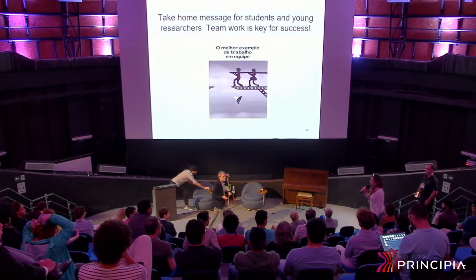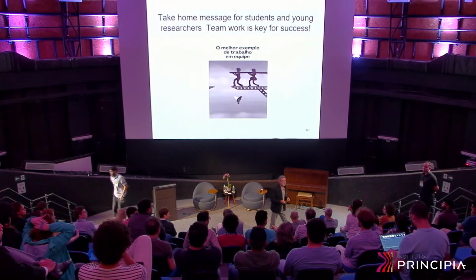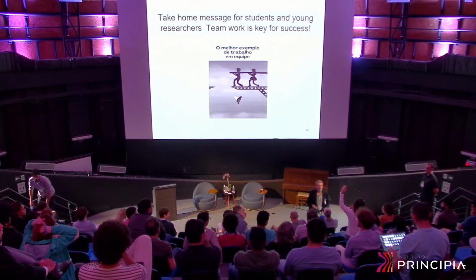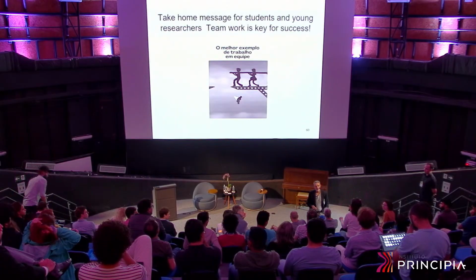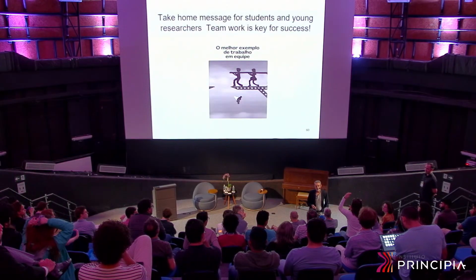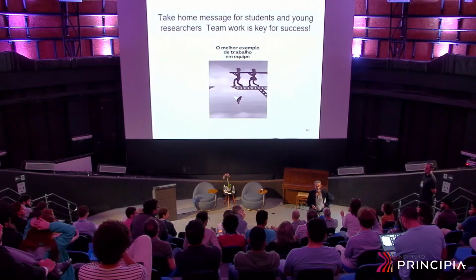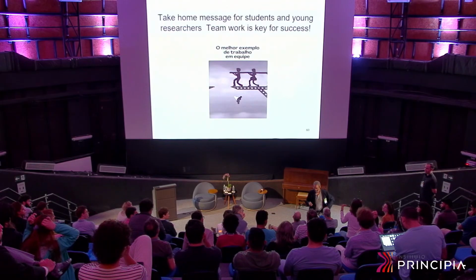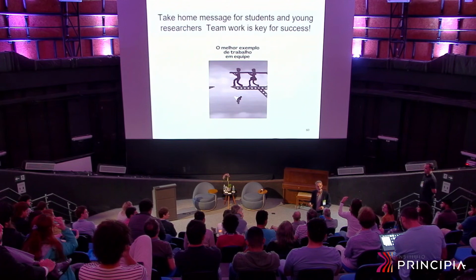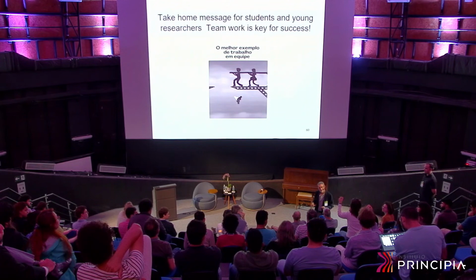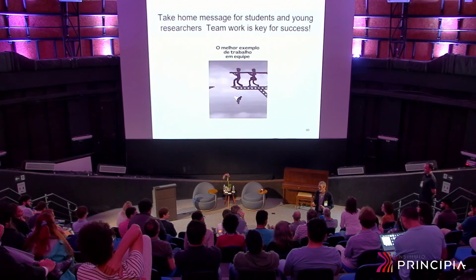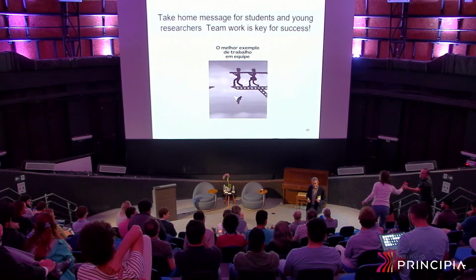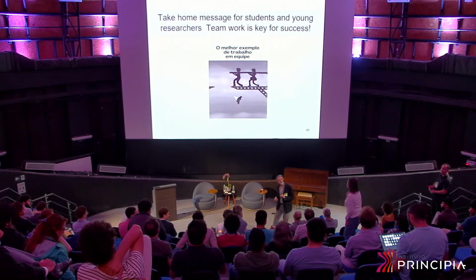Thank you, very nice talk. You had many orders of magnitude discrepancy, and you could finally come to an agreement by changing diffusion parameters and also the surface energy. By how much? Because I'm wondering, is it also orders of magnitude difference in the diffusion coefficient to fix that or not? No, it was a small difference in the surface energy.